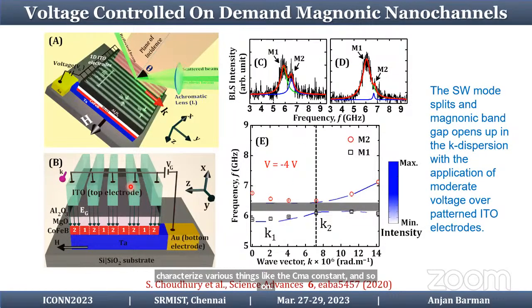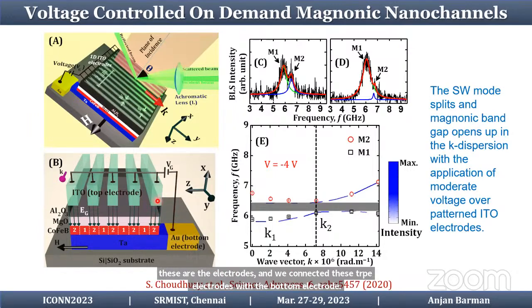Then we develop this system where you can see that we have patterned the aluminum oxide, with these ITO electrodes on the system like stripes. So these are the electrodes, and we connected these stripe electrodes with the bottom electrode, and now the electric field will not be everywhere, but it will